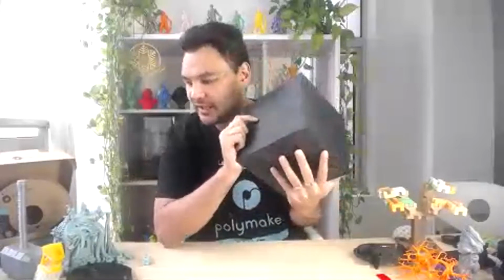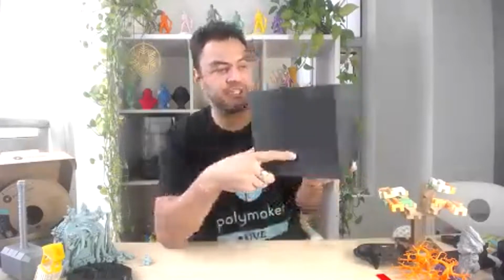There's no way, for example, with a polycarbonate, that you can do this. So why are we so proud of our nylon? It's very simple. You take very easy to print PLA. Tg is 60 degrees, so let's say heat resistant to 60 degrees. PETG, a tiny bit harder to print, but you have a slightly higher heat resistance, like 80 degrees. ABS, much harder to print, but you have 100 degree heat resistance. PC, more challenging to print, but you have 10 degrees more, 110 degree heat resistance.